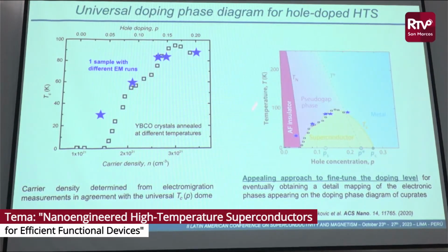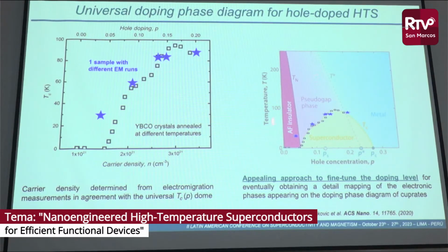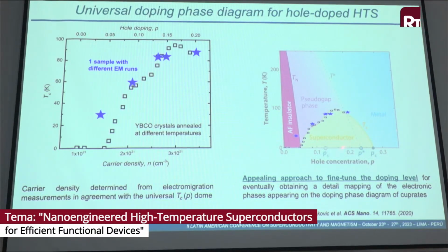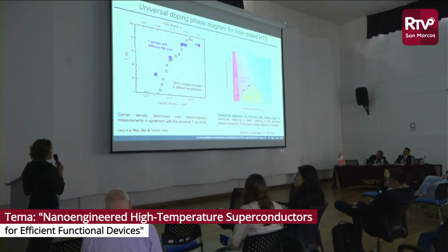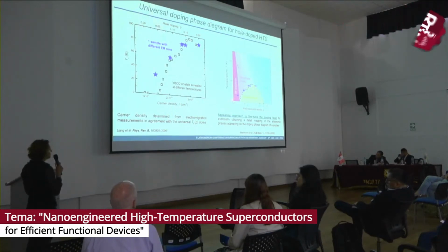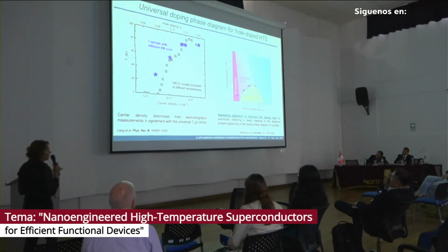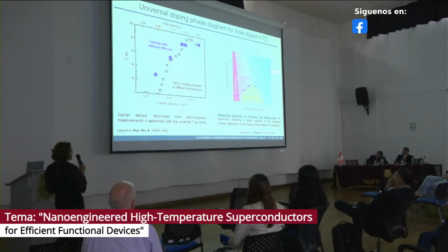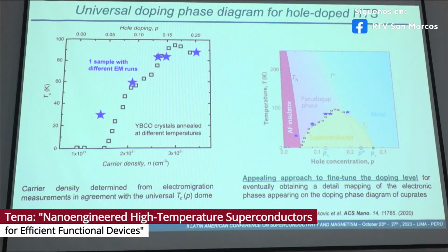And here is just this graph in the phase diagram, and what we can see here is that we can go from the superconducting metallic state to the insulating antiferromagnetic state by just playing with the oxygen content in the system, which is quite interesting to explore the different phase states, the complex phase diagram that we have in a high TC superconductor, in a simple sample.